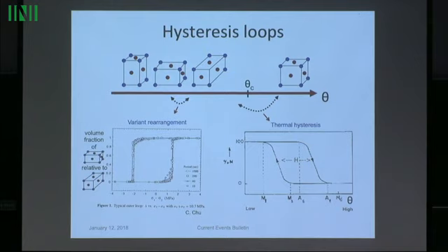That means that hysteresis in these phase transformations is, from a mathematical modeling point of view, not caused by some kind of viscosity or viscoelasticity. Because those kind of features in differential equations would have the property that if you went slower and slower around the hysteresis loop, it would collapse to zero. So it must be some kind of other explanation beyond, like the viscosity in Navier-Stokes. You can set up a cyclic deformation of a fluid, and you would see that property. But this case is different. It's called rate-independent hysteresis, in fact, this phenomenon.